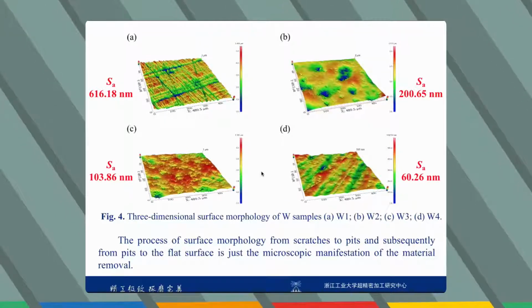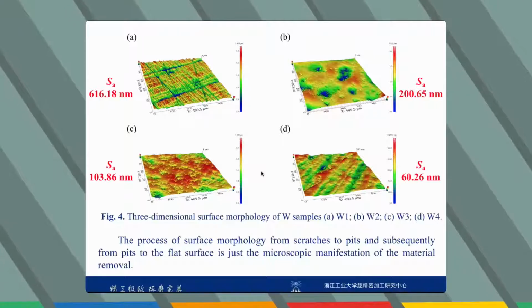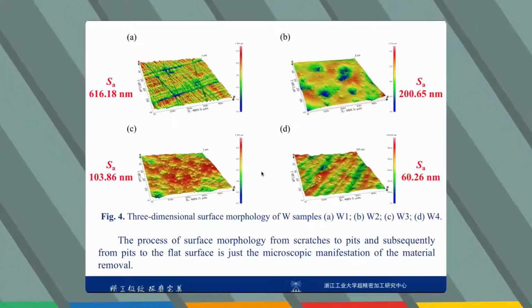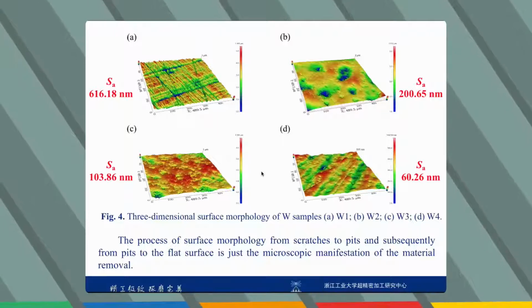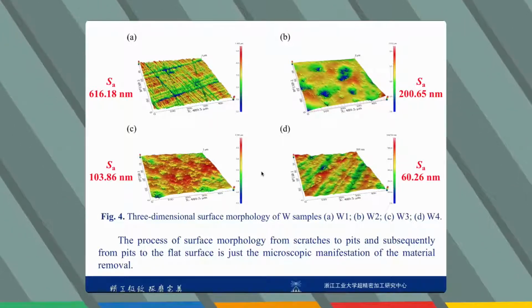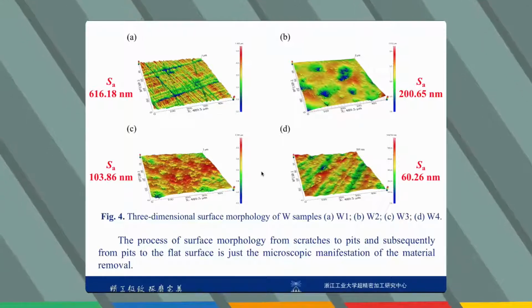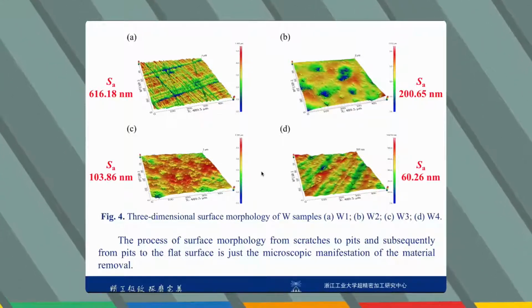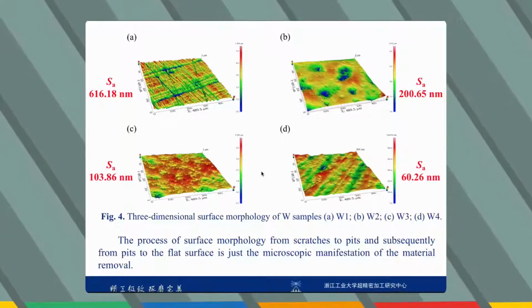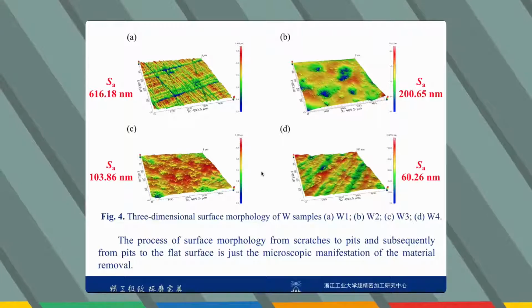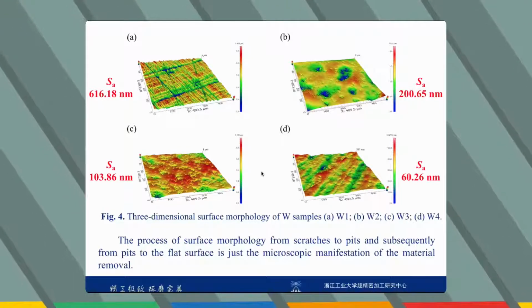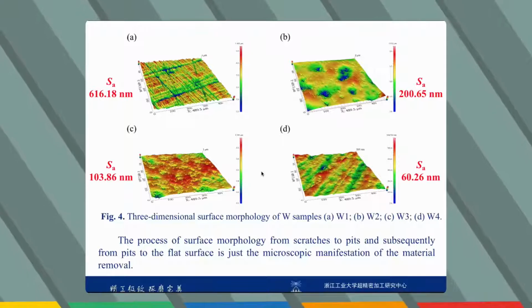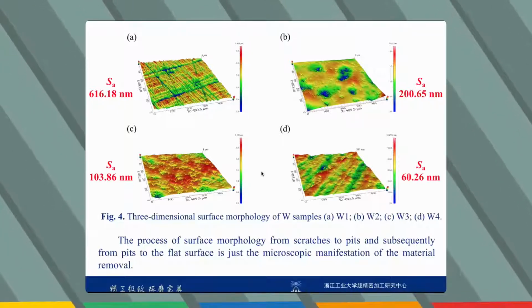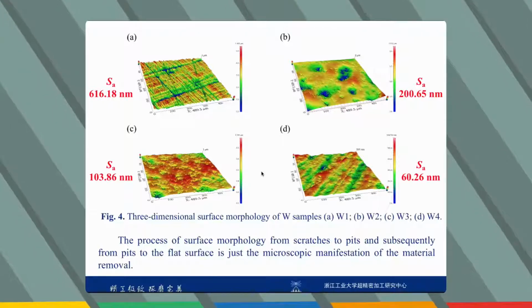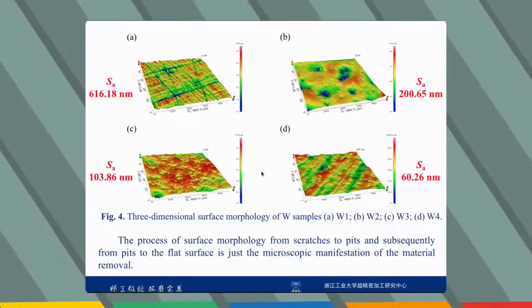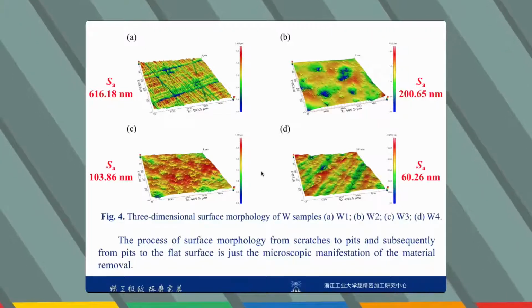Figure 4 shows the three-dimensional surface morphology of different tungsten samples after the polishing process. The surface morphology of samples tends to flatten out with the increase of polishing time. The unpolished sample W1 has numerous scratches on the surface, which are obviously visible in Figure 4A, while on the surface of W2 and W3, there are some large and small peaks. After 5 hours of polishing, the surface morphology of W4 turns relatively smooth compared with other samples.